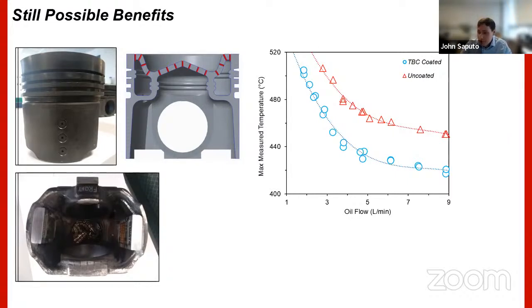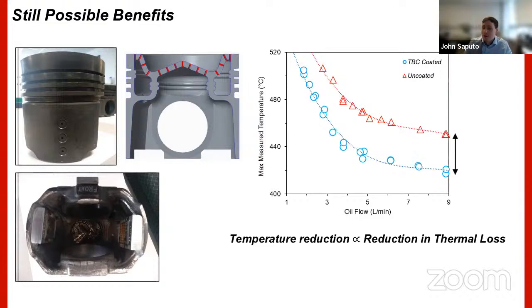So first, you notice that the temperature is reduced for basically every condition that we test in this. And a temperature reduction in these systems is thermodynamically related to a reduction in heat transfer losses. So you can do some basic math, and it'll tell you that you have about an 8% reduction in heat transfer in the system, which is interesting because in all of the engine tests that we do, you don't see any performance benefits. So what that tells you is that even though you're reducing the heat transfer through the piston by 8%, none of it goes to work, which is kind of interesting.